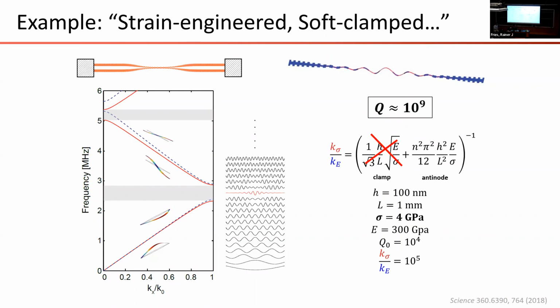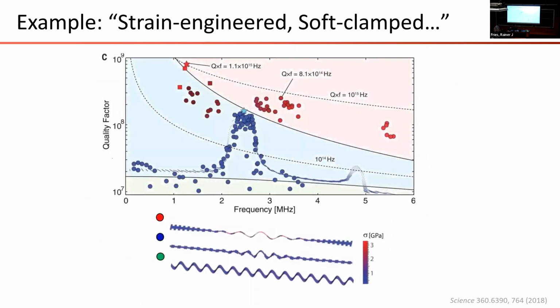And so this is a cute technique because simultaneously, if you change the pitch of the phononic crystal, you can localize a vibrational mode in a region of high tensile stress. So this co-localization of motion and stress is something which we call elastic strain or strain engineering, which in conjunction with soft clamping is what gave rise to this Q of 10 to the 9 oscillator that I showed in the first slide. So all these fun techniques, you can play at the nanoscale with beams, really simple structure. This is all, by the way, matches just napkin models. It's really nice. It's a compilation of different effects.